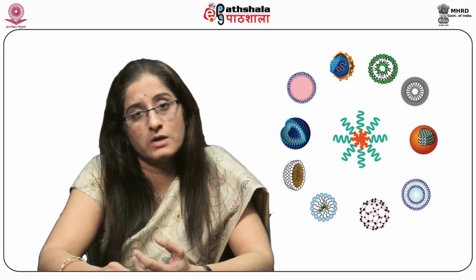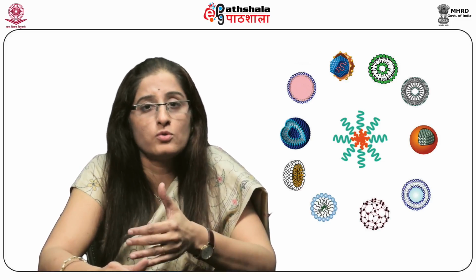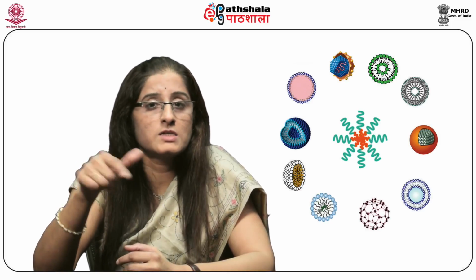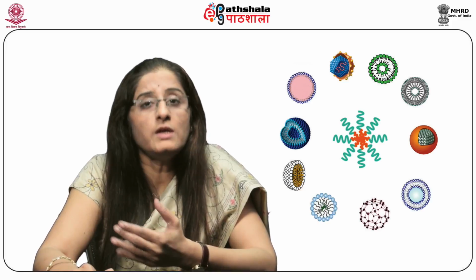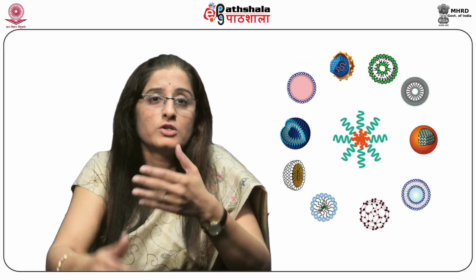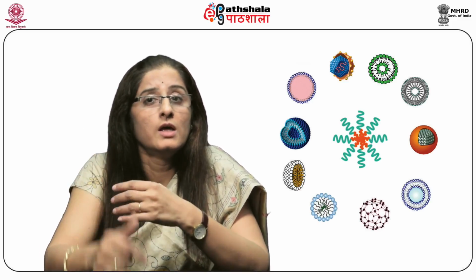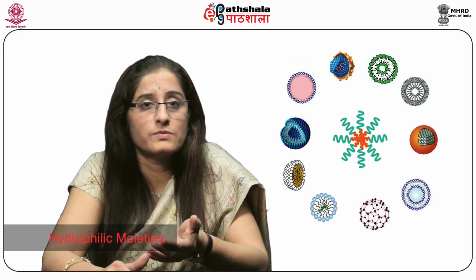Active loading of drugs through pH gradients involves the preparation of liposome in a buffer having low pH and then adjusting the external pH to 7 or higher. Subsequently, the drug is added and the dispersion is incubated for short periods of time. The lipid bilayer is generally impermeable to ionic molecules and larger hydrophilic moieties.